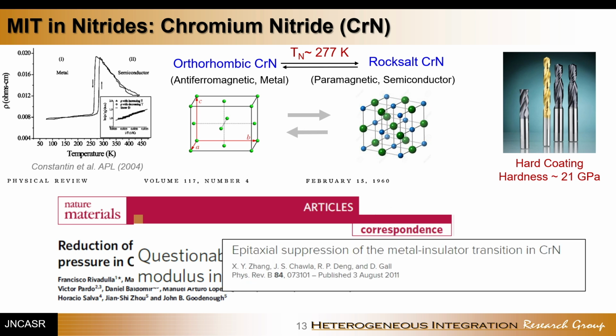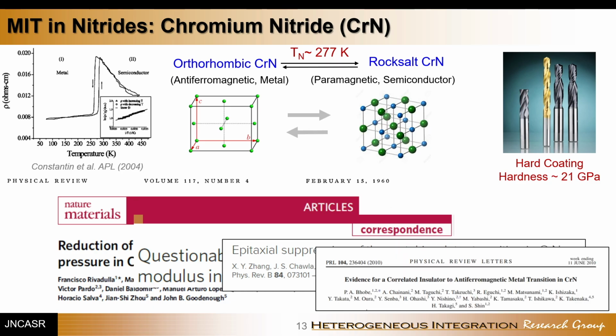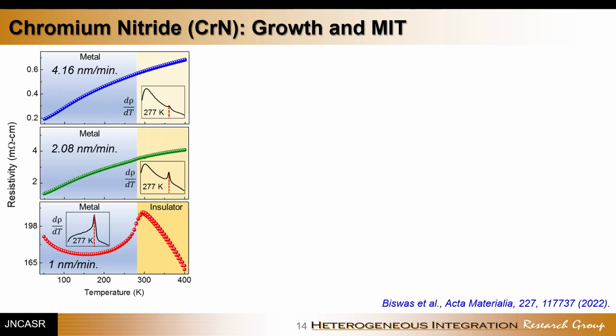And in case of thin film or heterostructure, you see there is always a debate whether the transition really exists or does not exist. So when we started working on this material, the first thing for us, of course, was to get the transition, or to get the reproducible transition. And what we realized is that although chromium nitride does show a metal insulator transition, it's extremely sensitive to its stoichiometry, very similar to VO2.